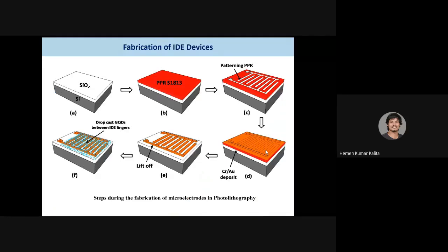IDE means interdigitated electrodes. So what is interdigitated electrodes? If you see figure number E, these are interdigitated electrodes. The electrodes line one another, one side is one contact and the other side is another contact. It's like a comb structure, two combs merging with each other, but not touching. So this looks more like a comb structure. Why do we use IDE structure? The reason is very simple: since quantum dots are very small, if we deposit them over a large area, there is a chance that they might not be deposited over some contact. So we have increased the chances of getting deposition by graphene quantum dots. That's why we have used IDE structures.